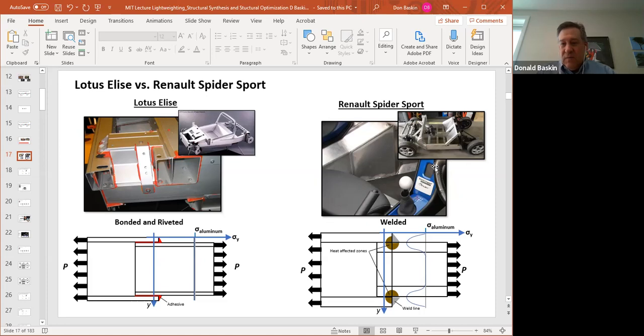So the Renault is welded together. They took these aluminum extrusions and they probably TIG welded or MIG welded them together, and they created these big heat affected zones. They found out that rather than the material having a strength that's up here, it actually had a strength that was down here. And because they can't selectively thicken the area where the joints are, where the structural members are welded together, they have to make the whole tube thicker, the whole structural member thicker, and they have to deal with the weight of all that.